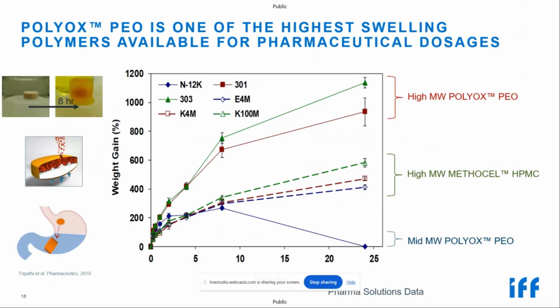The solid lines show POLYOX PEO. Green here is the highest molecular weight we have for pharma, 303, and red is another high molecular weight, 301, of 4 million. And you can see that their swelling is very rapid, and they continue to absorb water even at the 24-hour mark.